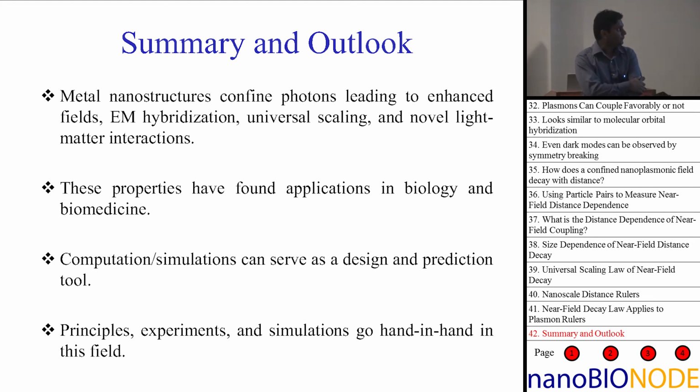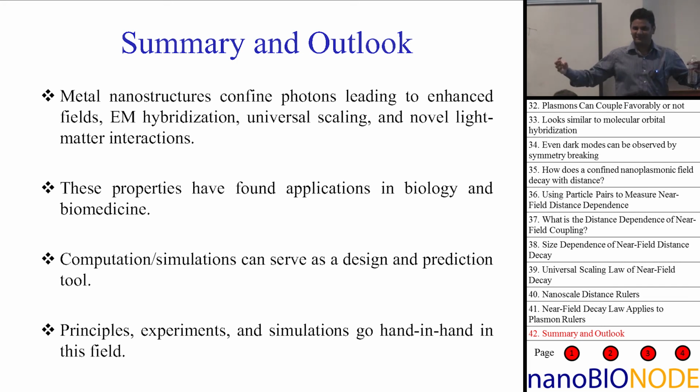Good question. So it turns out, very preliminary work. I'll just show you. That's the separation. That's the diameter. Those are the two parameters here, k and 0.2. Those are observables, experimental. It turns out that this factor 0.2 does not really change if you add more and more particles in the assembly. So that comes from the scaling of the problem.